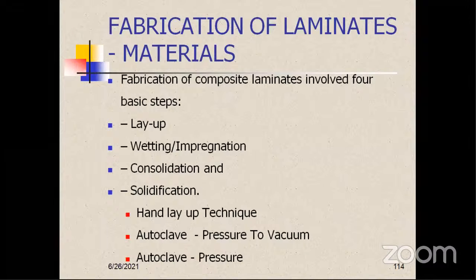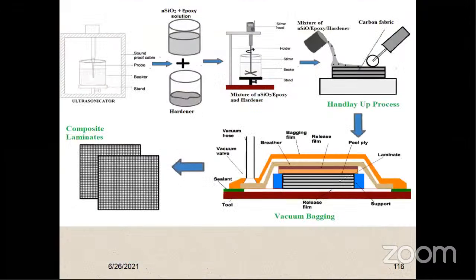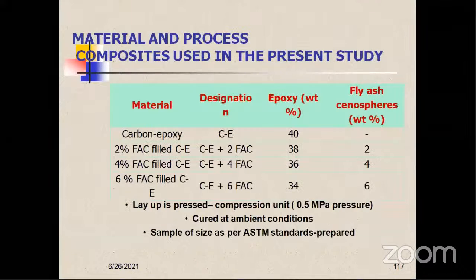So coming to fabrication, many methods are available. In our research work, we followed these, and some of the materials we formulated are carbon epoxy with 40% epoxy and 60% carbon. Then we added a secondary phase, that is, a three-phase composite, by adding 2 weight percent of fly ash spheres, 4 weight percent and 6 weight percent. And we followed simple compression molding with hand layup procedure for fabrication.